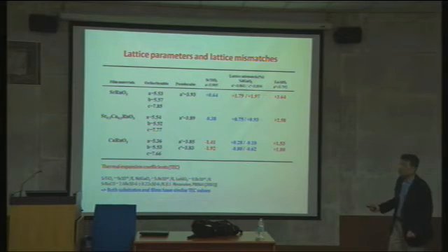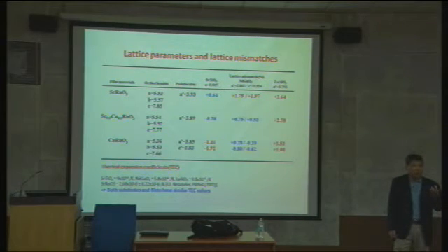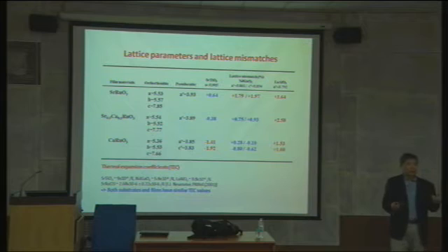But these are all the same perovskite structure. So for all perovskite structures, the thermal expansion coefficients are about the same in terms of lattice direction. But for example, silicon or metals are different. Silicon doesn't shrink that much. And that's why for any oxide film grown on silicon, you have tensile strain because they stretch it.